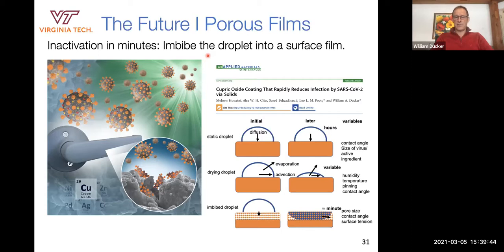It's the transport. So if you have a droplet that lands on a surface, you need diffusion between either of the virus to the surface or the active ingredient out to the virus. And diffusion over the length scale of millimeters is hopeless. You're never going to do, you know, that takes hours. You're never going to achieve that, no matter how good your active surface is. What we rely on, the reason why we're able to do it faster than that, is evaporation of the droplet. But relying on evaporation isn't that good.